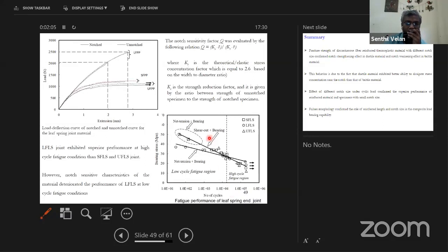The similar thing we were able to see here under low cycle fatigue behavior. The long fiber reinforced one shows a superior performance in the high cycle case, whereas in the low cycle the unreinforced material and short fiber material show even better performance. Again, it all depends on the notch sensitivity and the localized plastic yielding. That was the reason we saw at the specimen level itself. Now the same thing we are confirming at the component level or the machine element level.